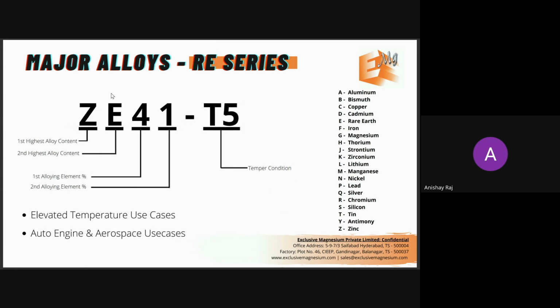And the third series is the rare earth series. This is a more expensive alloy, since you're using rare earth, and this is nothing complicated. This is just one of them. Zinc, and E stands for rare earth. So that's 4% zinc and 1% rare earth. What these kinds of rare earth alloys do is that they are use cases for elevated temperature use cases, right? So where the working temperatures are around 250 degrees, 350 degrees, and you still want the alloy to maintain strength and not lose strength through creep. That's where these rare earth series are applied.